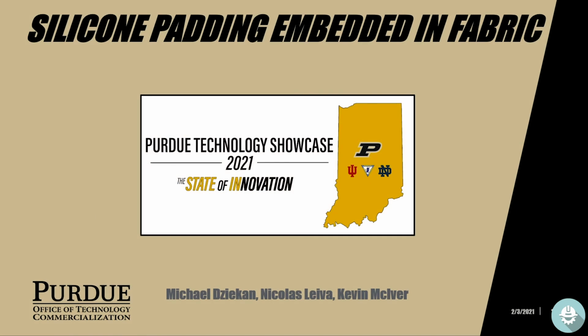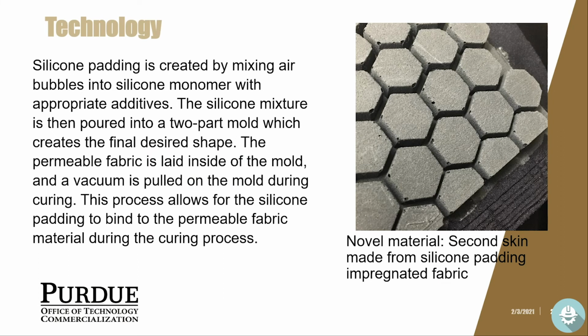We would like to present to you silicone padding embedded in fabric. Our technology centers around silicone padding, which is created by mixing air bubbles into a silicone monomer with appropriate additives. The silicone mixture is then poured into a two-part mold, which creates the final desired shape. The permeable fabric is laid inside of the mold, and a vacuum is pulled on the mold during curing. This process allows for the silicone padding to bind to the permeable fabric material during the curing process.